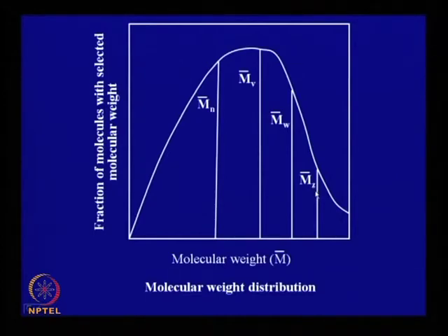This shows that Z average molecular weight is higher than weight average molecular weight, than viscosity average molecular weight, than number average molecular weight. So, number count gives you the determination of molecular weight of a polymer sample having low molecular weight species, low molecular weight polymers. For a high molecular weight sample, if you want to measure the molecular weight by the number averaging technique, the result will be wrong, misleading.